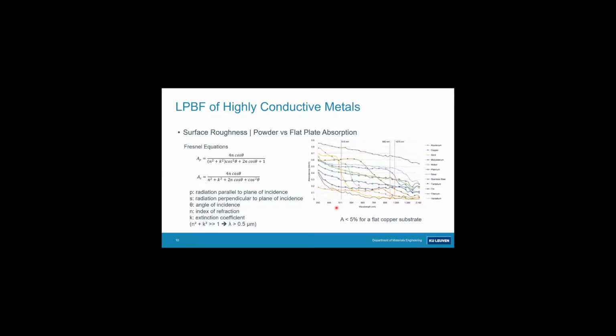Now for flat plate absorption, you have the Fresnel equations, which are only valid for wavelengths above 0.5 micrometer. And when you plot them for different materials, you again see similar curves as I've shown before. And you see, for example, copper here has a fairly low absorption at the infrared laser wavelengths. So you see that other elements absorb much better, and that's usually why titanium alloys or iron or nickel-based alloys don't exhibit too many problems when processing them in terms of absorption, and in terms of power you have to supply when processing with a near-infrared laser, but copper, silver, and gold are problematic.